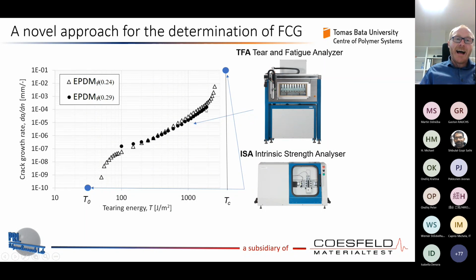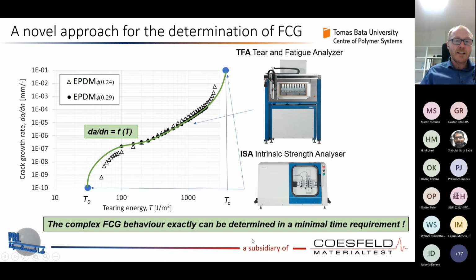define everything. So if we have another material like this EPDM with fill fraction 0.29, this is the black one, we can determine this stable crack growth with the tear and fatigue analyzer. And then with the intrinsic strength analyzer, we can determine these 2 points for the EPDM. And that means if we have that, now we have that parametrical function for the first material. We can change the parameters, fill it with the data we have already obtained with the ISA and tear and fatigue analyzer, and then make the complete function as it is. And that is what we need to do. The complex fatigue crack growth behavior can be determined exactly in minimal time using these 2 pieces of equipment, and we can have a very exact, complete fatigue crack growth curve.